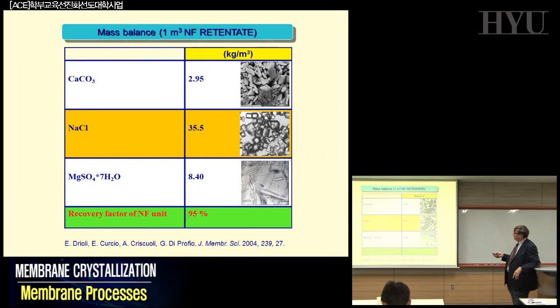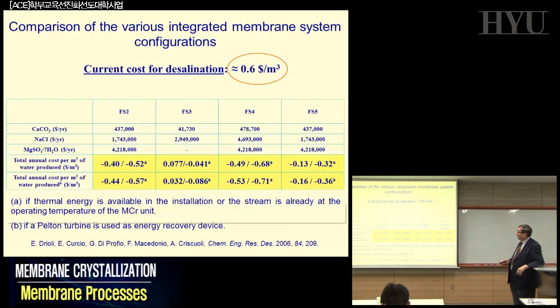And the story is that today, with membrane distillation and membrane crystallizer, we can have an overall recovery factor, for example on the NF unit, of about 95%. And for a single cubic meter of water, you produce not only water that goes to the RO, but also about 8 kilograms of epsomite, 35 kilos of sodium chloride and about 3 kilos of CaCO3. So using this integrated approach is becoming quite interesting.